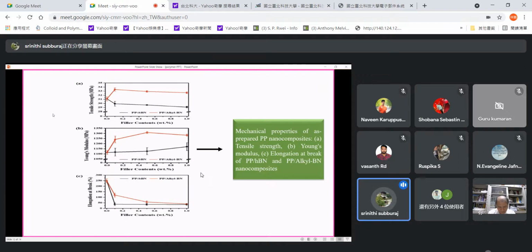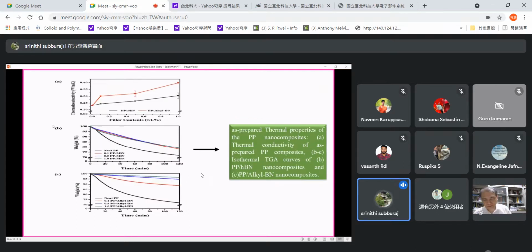So although the maximum tensile strength value was obtained with alkyl boron nitride, in this study the optimum alkyl boron nitride content to give maximum mechanical strength might be smaller than 0.1 weight percentage. So this is the thermal properties.